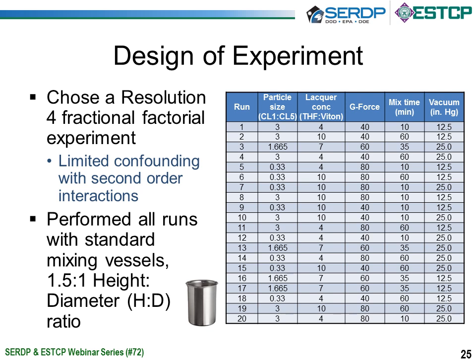As you can see, we developed a 20-run design of experiment where we altered our particle size distribution, the class 1 to class 5, from 3 to 1 to approximately 1 to 3. Our lacquer concentration was 4 to 1 to 10 to 1. We varied our G-force from 40 times the force of gravity to 80 times the force of gravity, changed our mix time from 10 minutes to 60 minutes, and then we did two vacuum levels where 25 inches of mercury is full vacuum and 12.5 inches of mercury is a half vacuum.